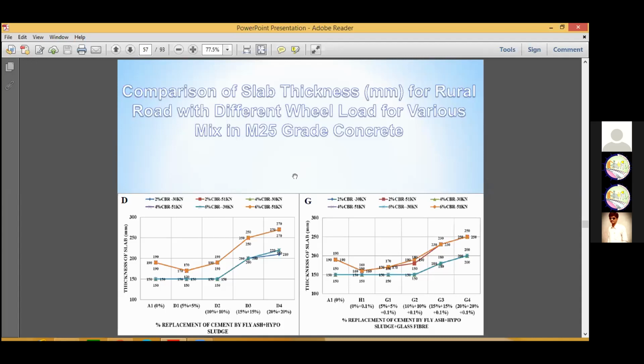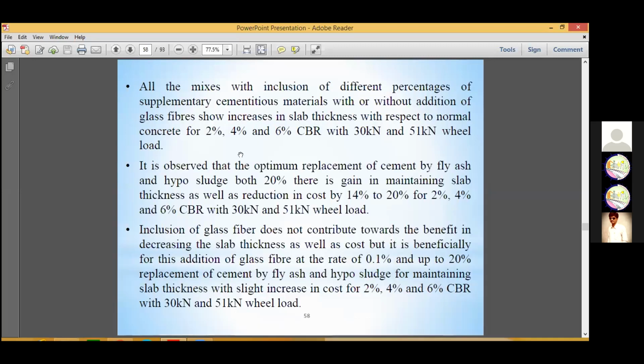As per this figure, you refer to the graphical representation. So A1, B1, B2, B3, B4. If your concrete quality is poor, then the thickness of the pavement is increased. If your CBR value is less, then also the thickness is affected. So for the CBR, if the ground is hard, then your pavement thickness is less. In the same way, refer to the 14 to 20% for the 2, 4 and 6% CBR with the 30 kilonewton and 51 kilonewton wheel load.